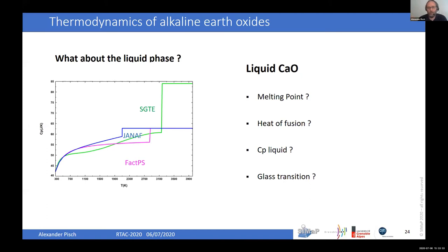So the question is now, which is the good melting point? Which is the good CP in the liquid? Which is the good heat of fusion? And where is the glass transition? So four questions in principle you should always ask when you have an extrapolation of the liquid phase down to room temperature. In this case, it's not straightforward because you cannot make an amorphous lime sample. It's physically impossible. And even in calculation, it's impossible. We did not succeed in ab initio molecular dynamics calculation to go down to room temperature.